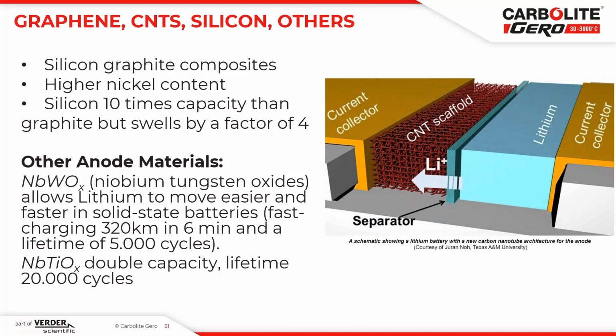So additionally, there are materials like niobium tungsten oxides or niobium titanium oxides. And because of the oxides, they have, let's call it like a big cloud of electrons around the oxygen, around the oxides, and this allows to move the lithium easier and faster through the batteries. In this case, it is a solid-state battery, and here the fast charging might take place within 6 minutes. And therefore you could run your car about 320 kilometers already. And the lifetime of such materials is not well explored, but already explored with around 5,000 cycles. And the titanium oxide based material has a lifetime of around 20,000 cycles and the double capacity. So this is very interesting materials under development.